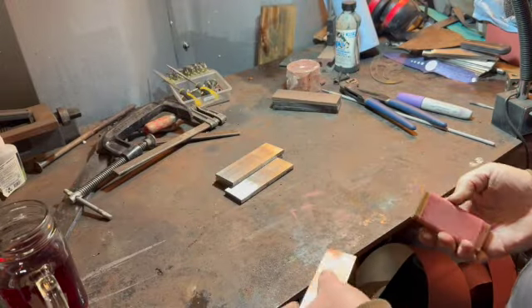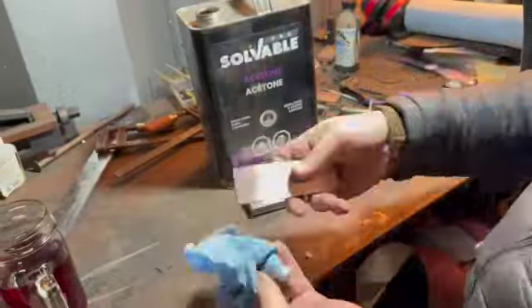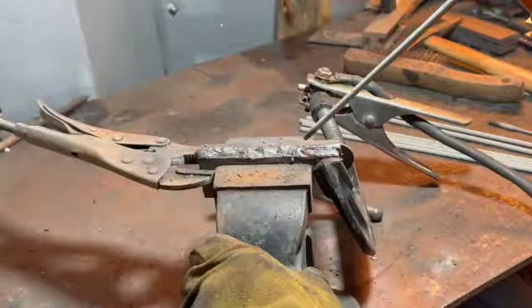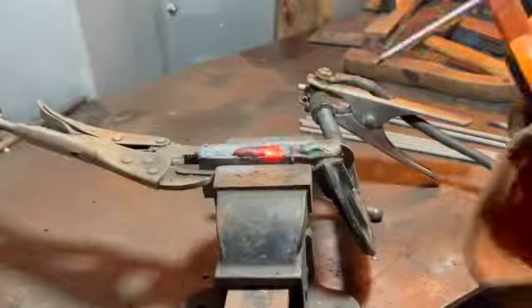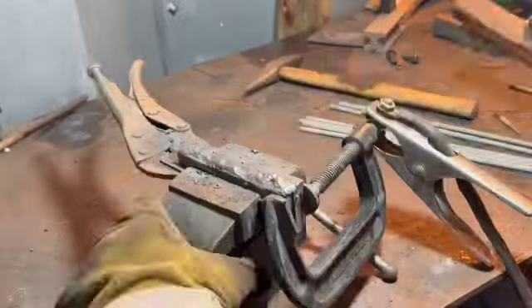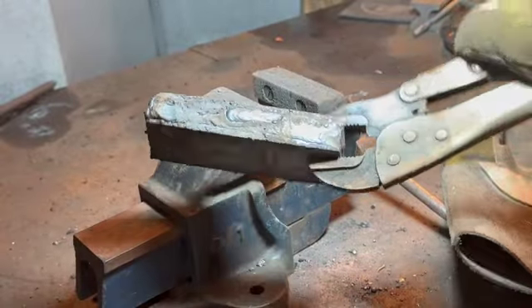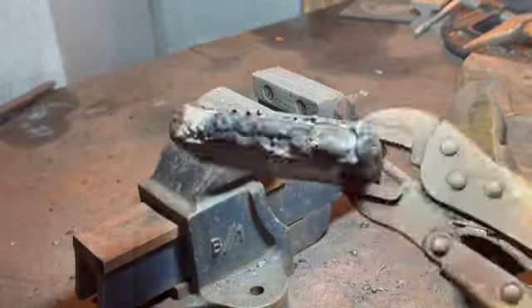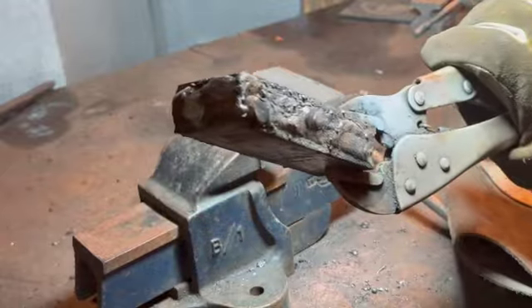We're going to weld up all sides of this. We need to completely seal it so that the copper won't melt and run out of the billet. They're not the prettiest welds, but I've completely sealed up all of the seams so we have an airtight billet.